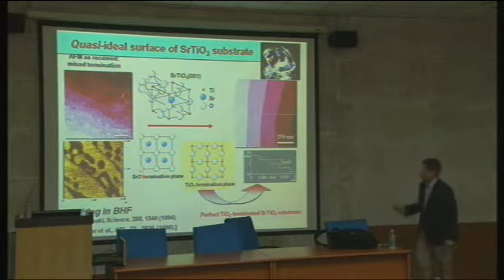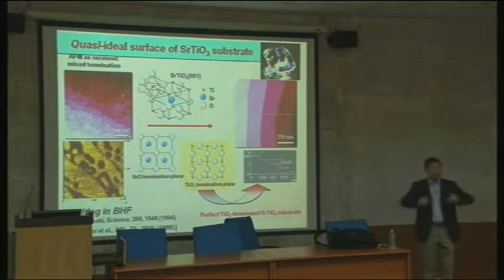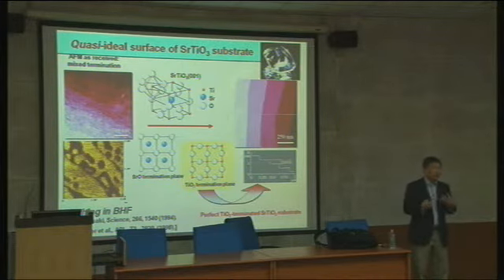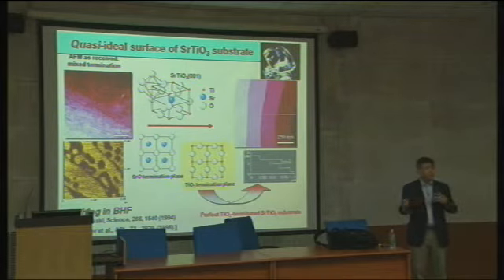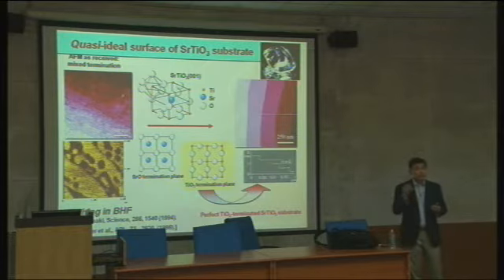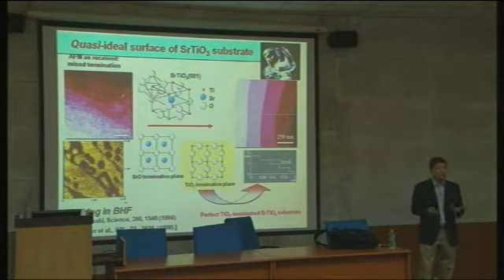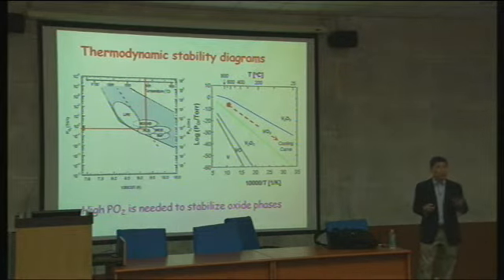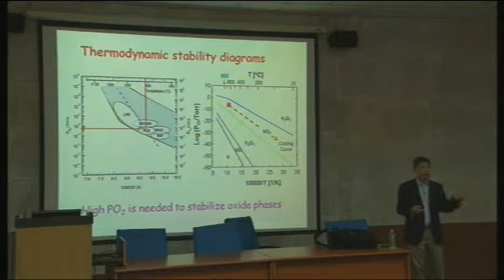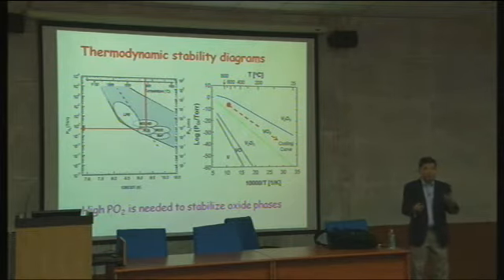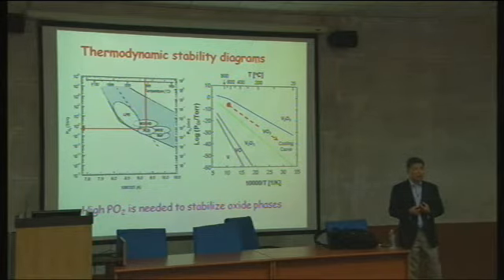The next thing you do is not only use the substrate, you have to grow thin films with real atomic layer control. Then how do you know you have this atomic layer control? We adapted a technique from MBE, molecular beam epitaxy, the semiconductor growth. They use what they call an in situ monitoring technique, reflection high energy electron diffraction, which monitors the growth in real time: how fast you grow, what the structure is. We call this real-time monitoring of the growth. But we cannot use those monitoring techniques directly. They're available for MBE, where the growth condition is ultra high vacuum, which means you don't want any gas, like an atmosphere, just purely high vacuum.